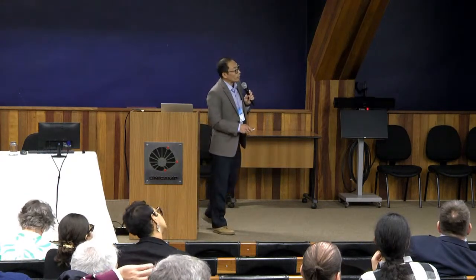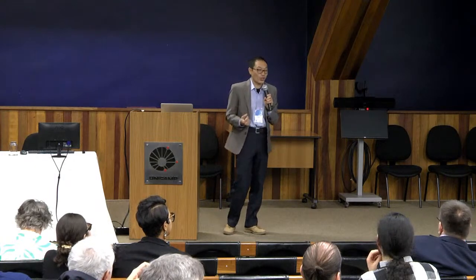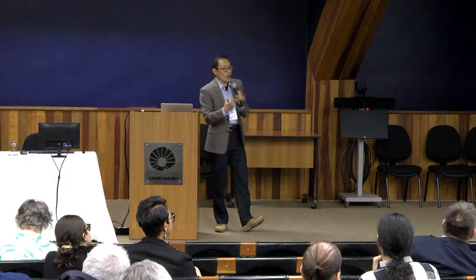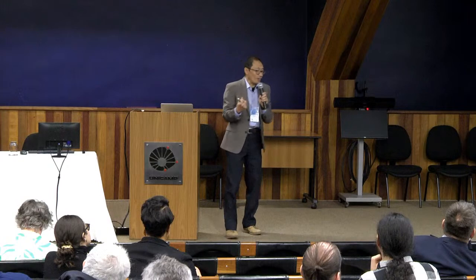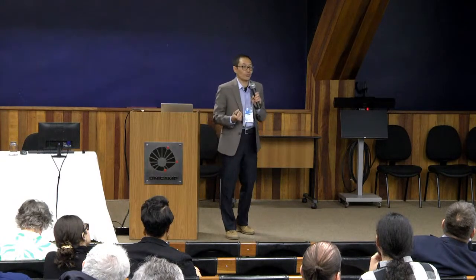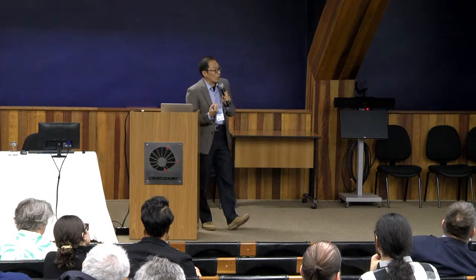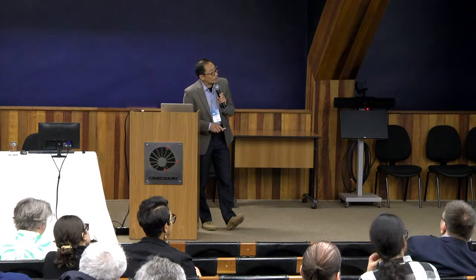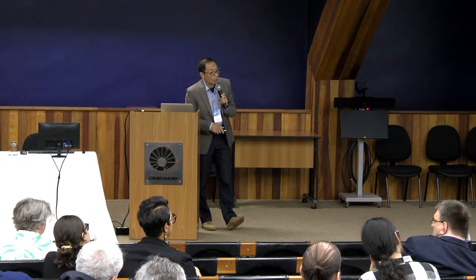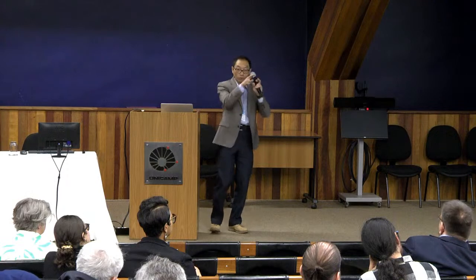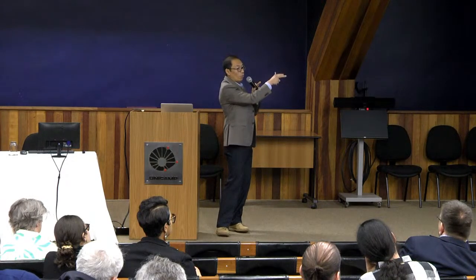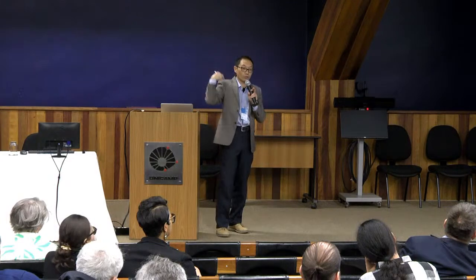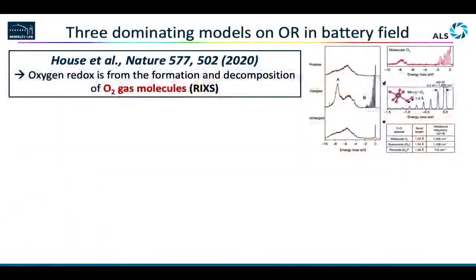One of the critical techniques used in his work, I believe done at both the Swiss Light Source and the Diamond Light Source, is high resolution RIXS, to resolve the vibronic mode of the features. I showed you there are features at 531 eV, and also a feature close to the elastic peak. We saw those over many years. They always show up together.